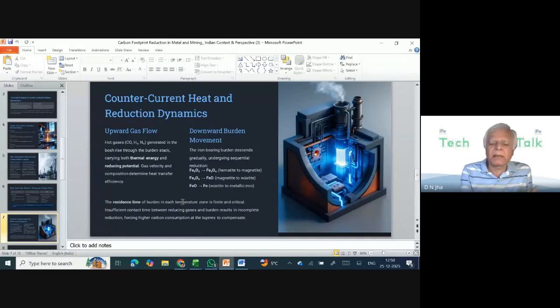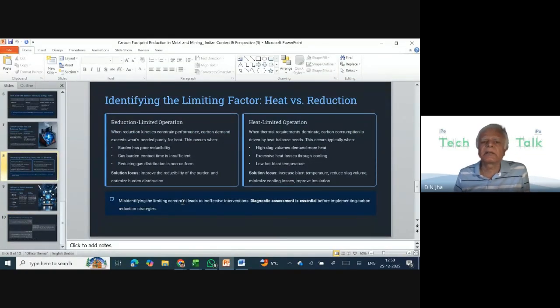This is important because if we look at the Indian scenario, you will find that the Indian iron ore is not the best that is available. That's bad news, but nonetheless, we have to utilize the very ore that we have within the country economically. There are strategies or methods through which we can improve the reducibility of the charge. And if we improve the reducibility of the charge, and the reduction is constant, then we are bound to have a carbon rate reduction. And frankly speaking, this is a path where I think we have tremendous potential within India to reduce the carbon.